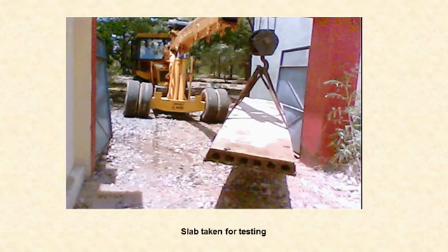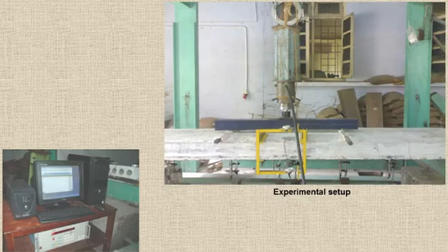So the slabs were tested on a loading frame. This is the experimental setup. The load cell was there to record the loads, and LVDTs were kept to measure the deflections. And this is a curvature meter fabricated to measure the strains, and a data logger was used to record the load and the deflections.